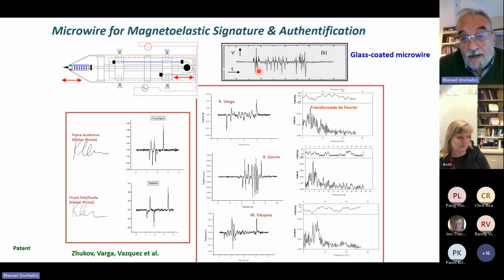So what we found is that for each person, this magnetoelastic signature is not always the same. It depends on whether you are very happy, in good humor, or not so good, and you have some differences. But what is clear, what characterizes your signature, is the number of peaks and the trend. It is not so important the strength, the intensity of the peaks and the total time of the signature, but the trend of all these peaks.